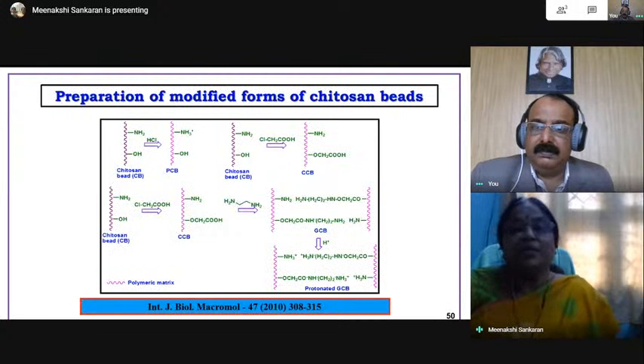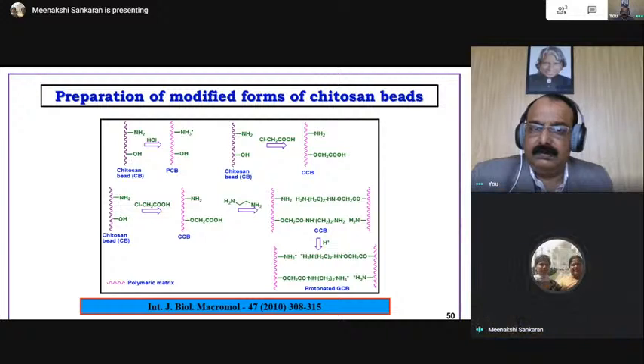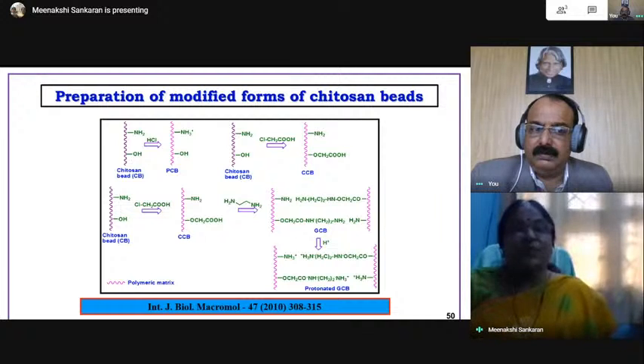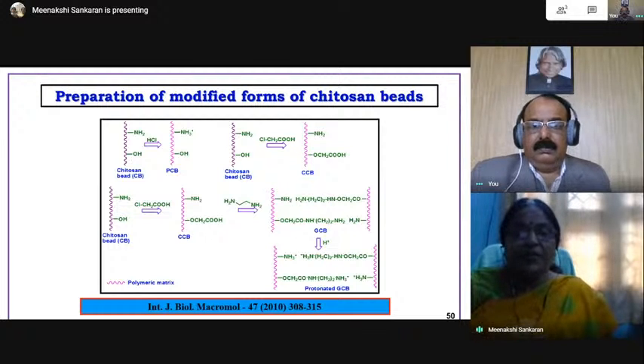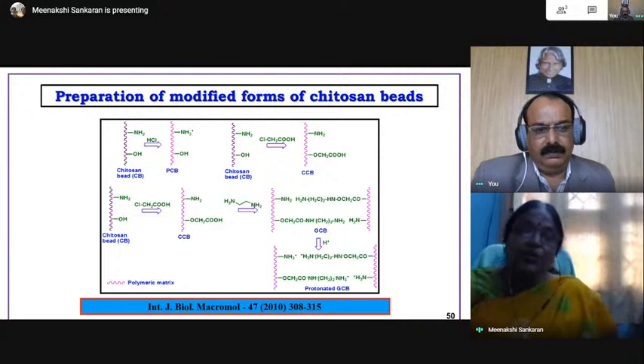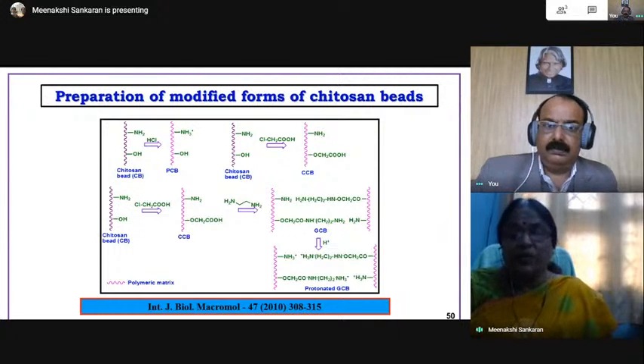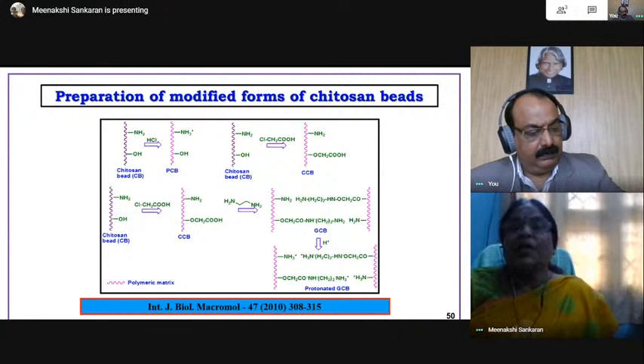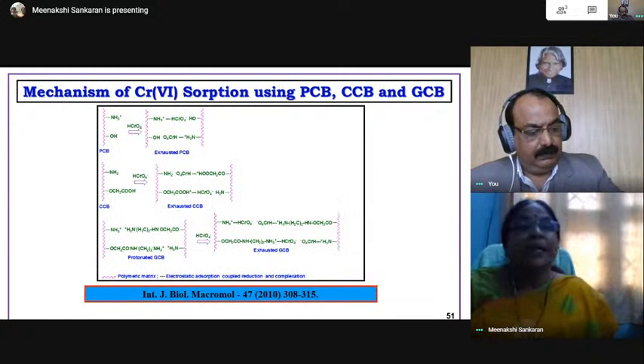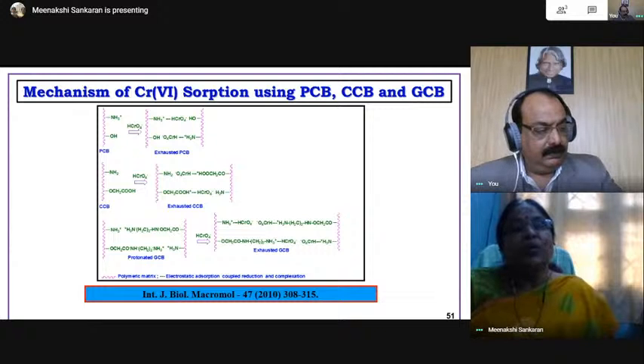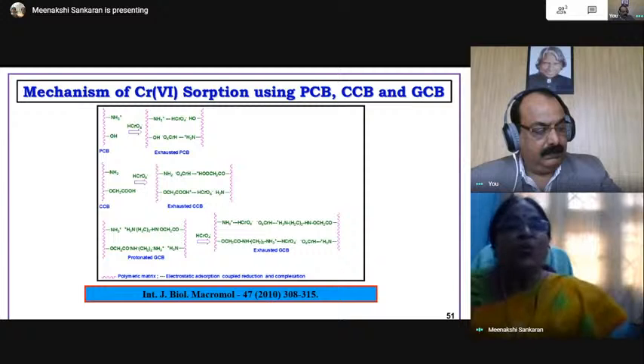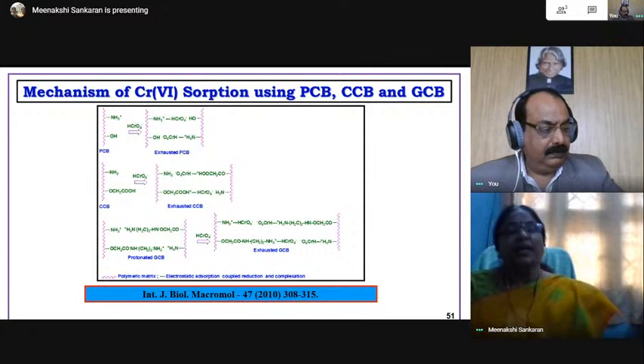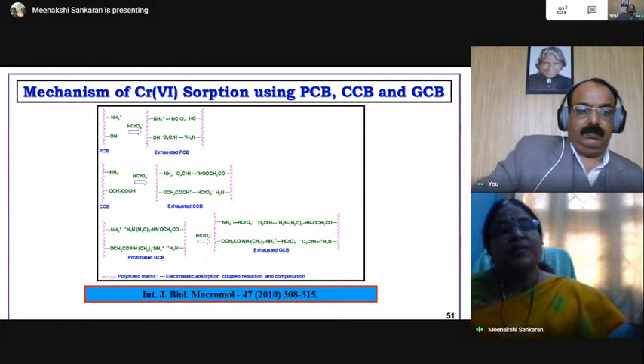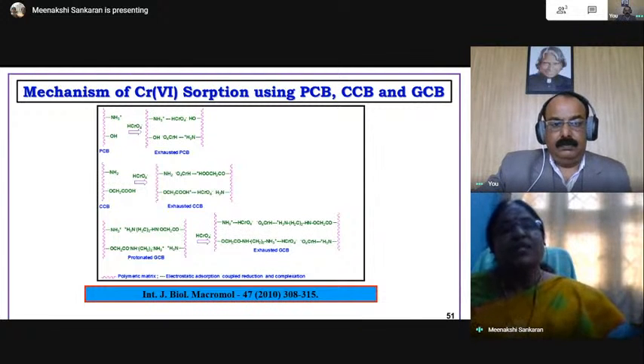And we have used chitin and chitosan again for heavy metal removal. We have modified chitin and chitosan according to our need. These are the various forms, that is protonated, carboxylated, and we have introduced many amino groups into our polymeric chain, so that we have enhanced the amino groups in the chitin and chitosan, which in turn enhanced the removal capacity of heavy metals. And in heavy metals, major work has been done on chromium 6 removal. Chromium 6 is highly toxic, and earlier we observed chromium 6 ions in drinking water because of tannery pollution. So we have concentrated mainly on chromium.